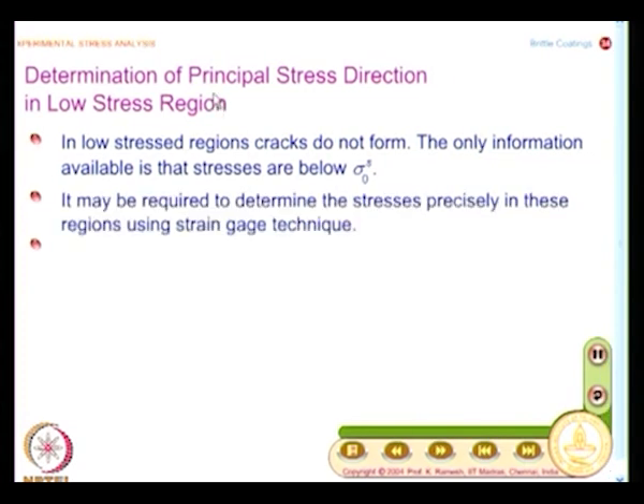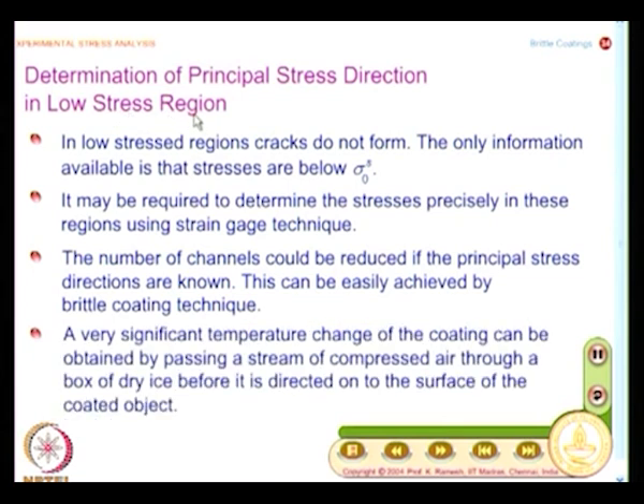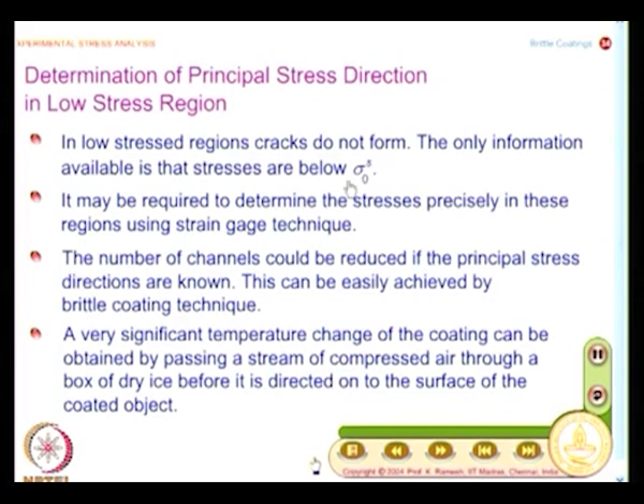So, we are going to find out the principal stress direction in low stress region, that is my interest, because when I want to do optimization, I need to scoop out material from low stress regions, and what you have is the cracks do not form in the low stress region, and the only information that you have in those regions is that stresses are below sigma naught s, because we have already seen there is something called a failure strain of the coating. We have also looked at what is the failure stress of the coating corresponding to the failure strain, and we have also looked at what specimen stress has caused the failure of the coating, we call that as sigma naught s. So, now we know from the appearance of no cracks that the stresses are below sigma naught s.